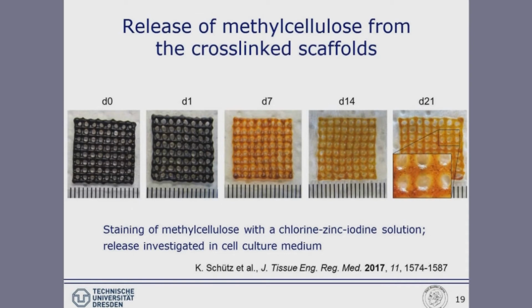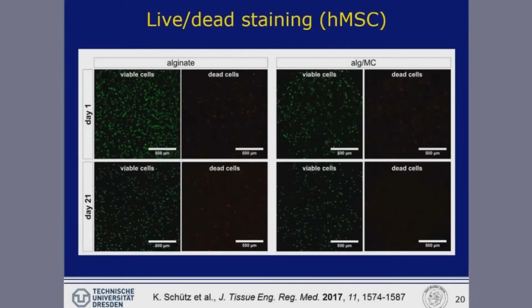And therefore, the viscosity is again going down towards a region which is necessary for long-term cell survival. But the scaffold, of course, due to the cross-linking of the alginate part, still is stable, and so we can culture the structure over several weeks without any risk of decomposition. This works well. We tested this with primary human mesenchymal stem cells.